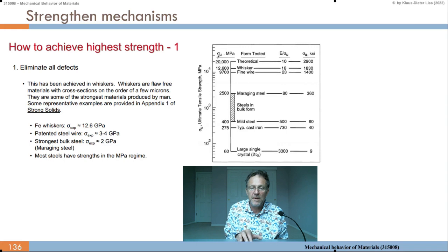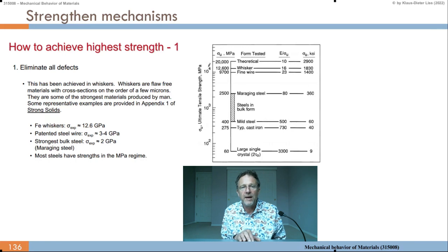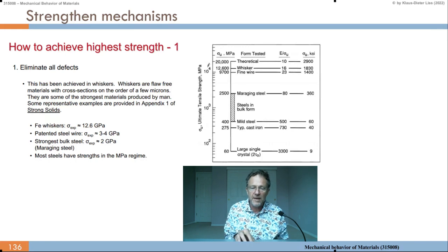We know the theoretical limit we don't achieve because we get dislocations. As said, the whisker is some of the strongest material, and this is because we have a relatively thin wire-shaped crystal and need to nucleate dislocations at the surface. If we look at the surface to volume or surface to cross-section ratio in the whisker, then we have a large surface energy, and therefore the nucleation of dislocations is difficult. The activation energy is large, so we get a high strength.